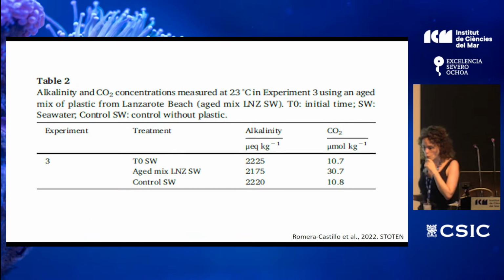Then we also wanted to know if this decrease in the pH was due to the production of CO2, or if it was also due to the production of organic acids released by the plastic. To do that, we measured the alkalinity in one of the experiments, and we also estimated the CO2 through the alkalinity and the pH. We estimated how much CO2 was produced, or the variation.